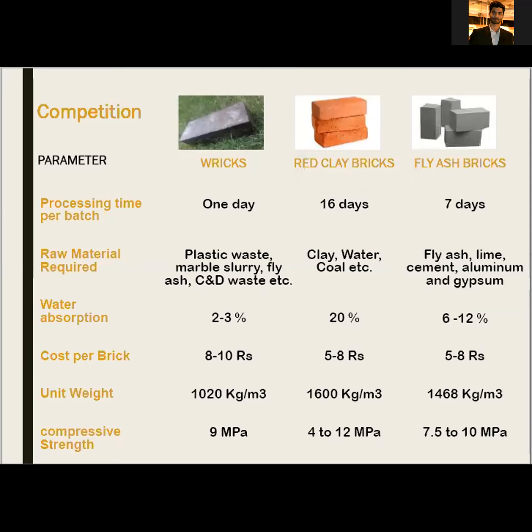The cost of the brick, in our case, at the prototype level, is going up to 8 to 10 rupees. So we will charge comparatively 8 to 10 rupees. Whereas with the red clay brick, it is variable as per the season. In dry season, it is around 5 to 6 rupees, and in rainy season, it goes up to 8 to 10 rupees. And in case of fly ash, it is available in those areas where the fly ash as a raw material is available, and there the cost is around 5 to 8 rupees. And if I talk about the unit weight, it has a lower density because we are using plastic. So it goes up to 1020 kg per meter cube, whereas bricks are heavier.